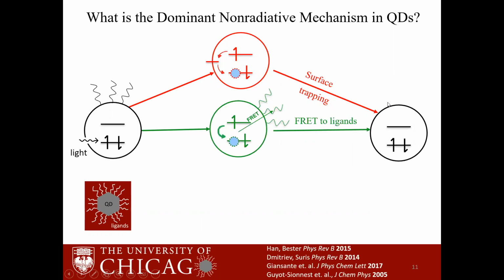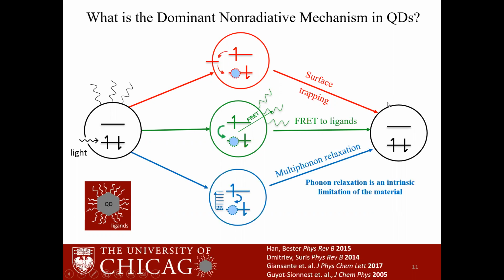The second mechanism is called FRET to ligands. In this mechanism, the quantum dot relaxes to the ground state and transfers its energy to the absorption of the ligand vibrations by a Förster resonance energy transfer. So Förster resonance energy transfer is a common energy transfer mechanism in which you have a donor and an emitter, and when they're really close together, the rate of energy transfer strongly depends on the separation. And this FRET to ligands becomes important as you go into the infrared because the absorption of the ligands starts to become stronger. And the third mechanism is unique to quantum dots emitting in the mid-infrared.